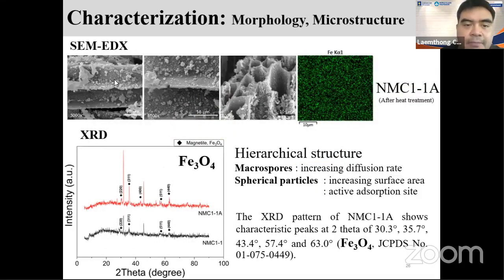From the SEM image, you can see a lot of particles on top of our precursor, because at the beginning, the sugarcane bagasse seemed to be quite smooth, right? When we use the SEM to see the morphology. But after the hydrothermal process, a lot of particles are trapped on the surface of this sugarcane bagasse. But this is not the iron particle. This is the carbon particle which is extracted from the cellulose.